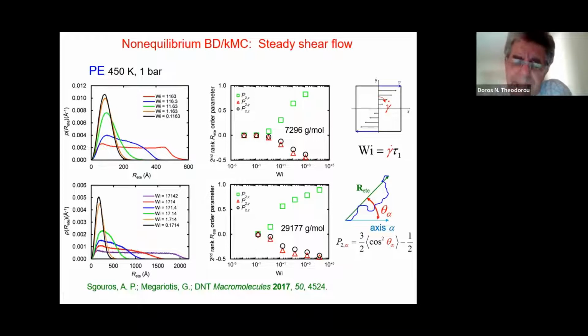And in addition, the chains strongly orient. What we show on the right-hand side is essentially second Legendre polynomials, which reflect the orientational tendencies of the end-to-end vectors of the chains. They are functions of these angles theta between the end-to-end vector and a coordinate axis. And we see that whereas at low Weissenberg numbers, this order parameter P2 is 0, there is no orientational preference for the chains. For strong flows, there is a definite tendency for the chains to orient parallel to the x-axis, the axis of the velocity, and normal to the y and z axis. Actually, there is also a small difference, as you see, between the y and the z directions, and this gives rise to what is called the second normal stress difference in these flowing melts, which is calculated along with the first normal stress difference in quite good agreement with experiment.